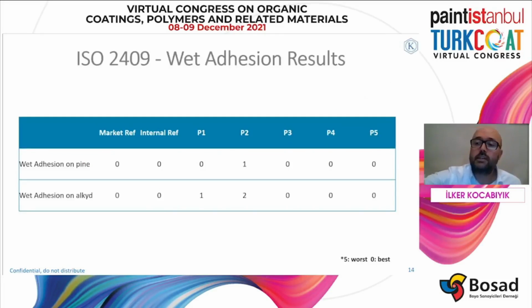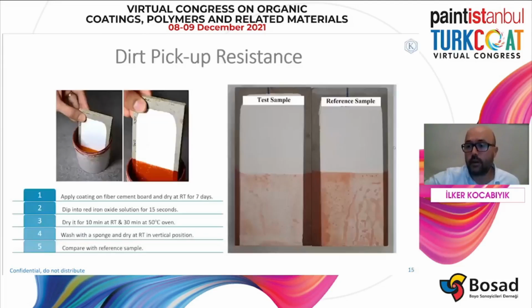Wet adhesion is tested on pine wood and also on solvent-based alkyd paint surfaces. After 7 days drying at room temperature, adhesion was tested by using the crosscut adhesion tester and rated with a 0 to 5 scale again. Almost all tested polymers show good wet adhesion on alkyd and pine surfaces. Both P1 and P2 showed slight deficiencies.